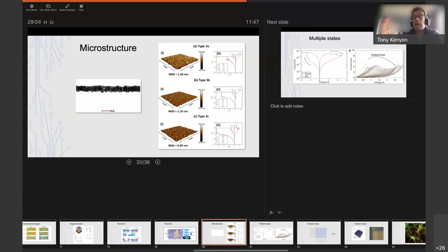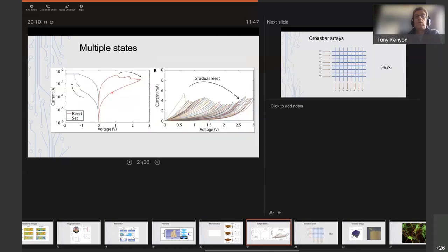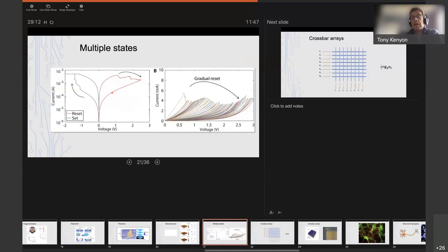So we've halved that electroforming voltage just by changing that roughness. We can also control very nicely by varying that roughness the voltages at which we then switch from the high resistance to that intermediate state. So now we can get that down at about a volt. In fact, we can do it less than a volt. And we can start to access not just two states, but multiple states. And here we have about 30 states, I think it is.